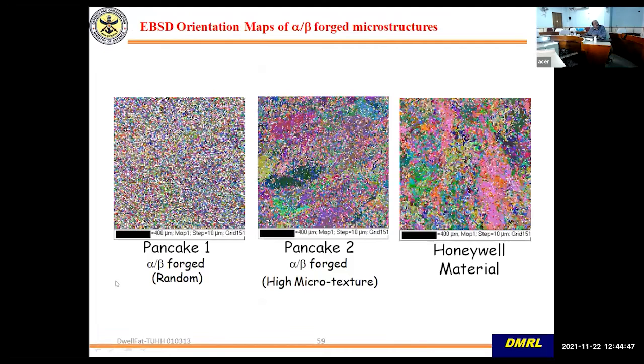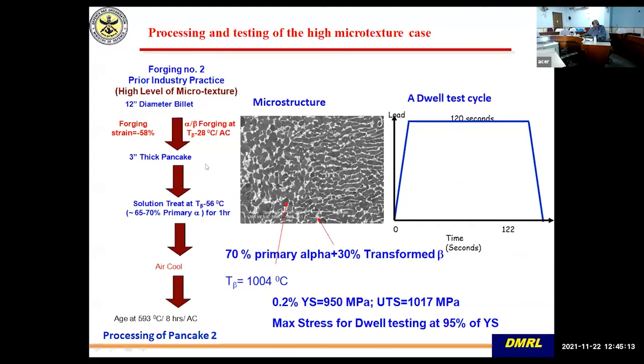So this is the pancake one. This is the randomized one. You can see the color is very mixed. There is no particular area where you can see a microtexture or a patch of color. As compared to that, in the one which has got higher microtexture, you can see similarly oriented grains in certain regions. This is called microtexture, also called macrozones, again in the Ladish material also. So let me show you the high microtexture material. This is the SEM microstructure. It has got a higher amount of primary alpha, around 70 and 30%, and so it was dwell tested.